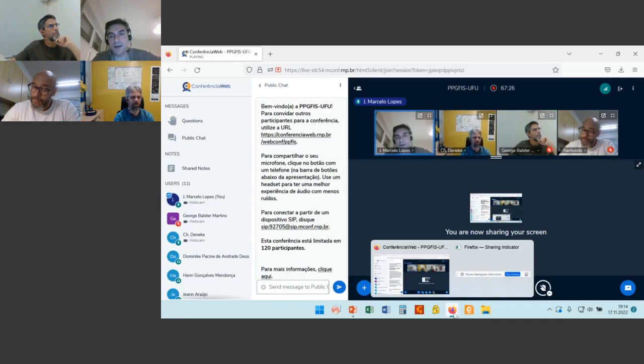You can grow some boron nitride, but it's low quality, maybe some polycrystalline material. So I'm skeptical that epitaxial growth will serve for all material systems. I believe that you could play a bit with what I presented today, selective area epitaxy, where basically you could grow over a wafer scale, but never really a thin film, growing very selectively on specific areas of the device and so on.